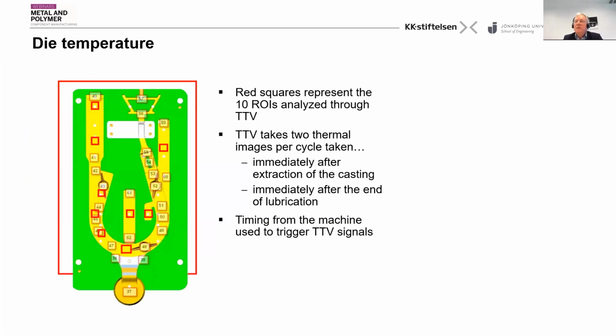What we did, in our tests on this test casting you already see here, was not measure the whole temperature, but concentrate on these small little red areas. The red areas were taken for process control or process monitoring. And we always take a picture immediately after extraction of the casting and at the end of lubrication. That's very important, so you can see what is happening with the die. Does it change in your process?